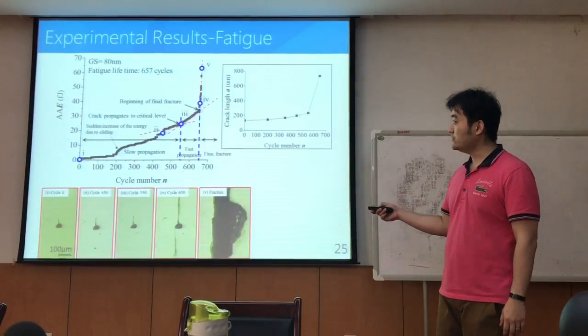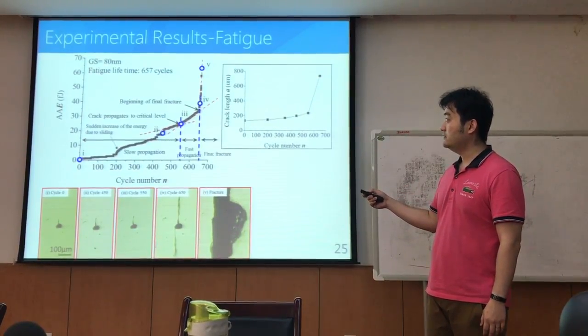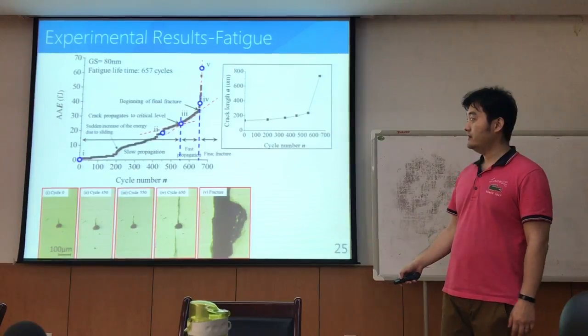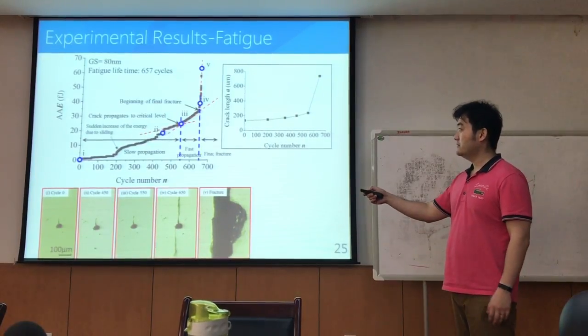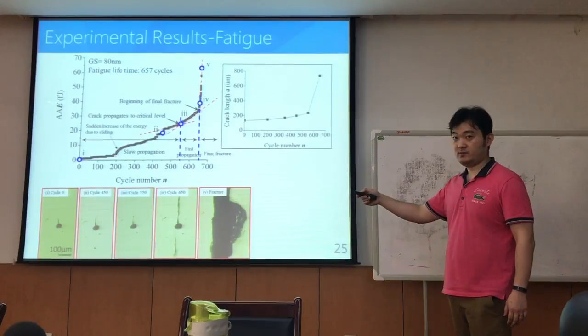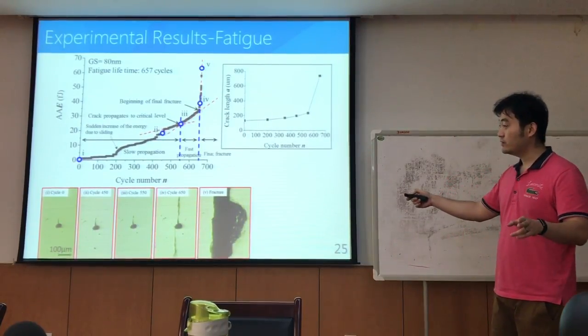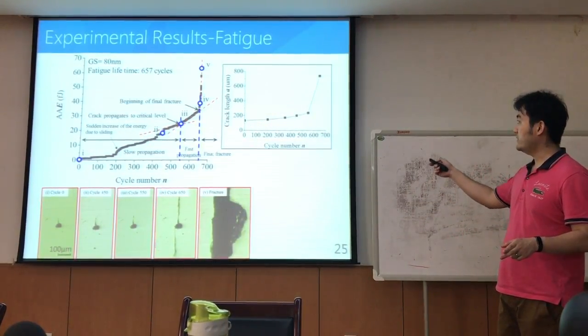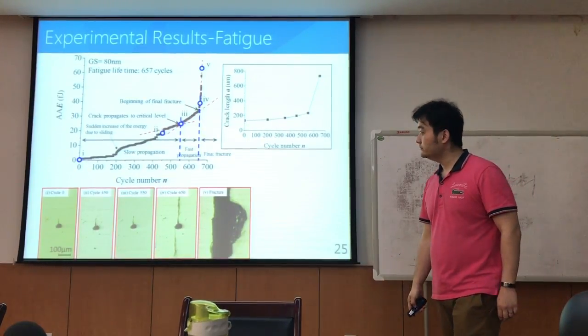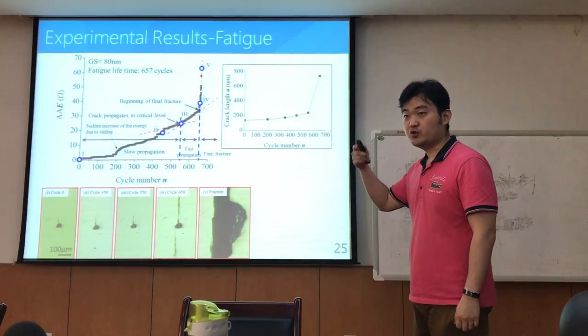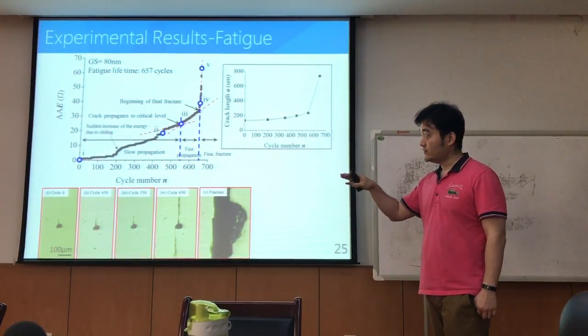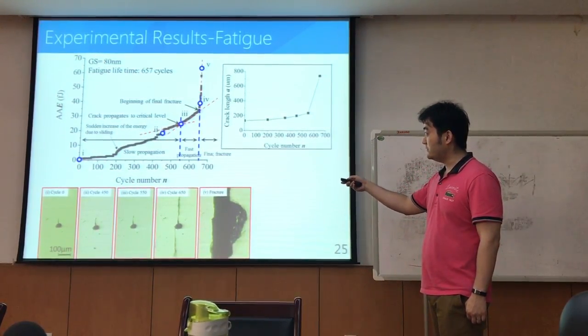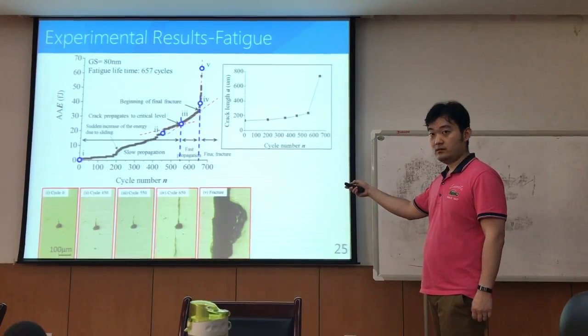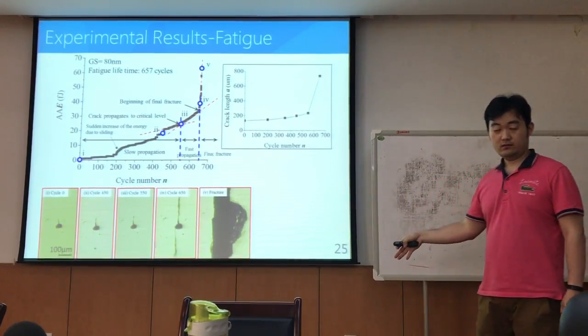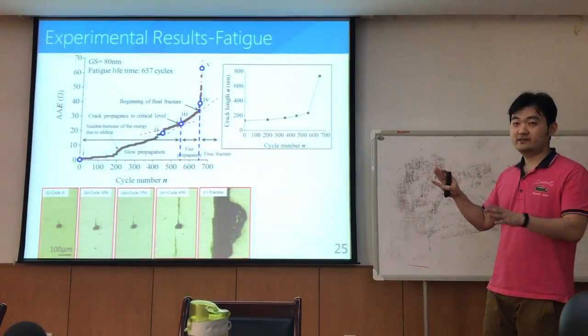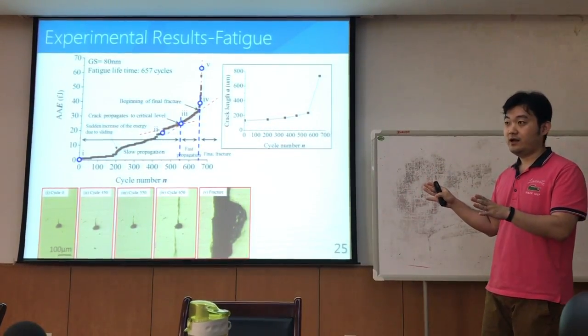And it also works for large grain specimens. Okay? So we can see this accumulated acoustic emission energy is highly correlated with the crack propagation speed. So we find a way to trace the fatigue process so that with this curve, we can predict the fatigue lives of certain nickel titanium shape memory alloy applications.